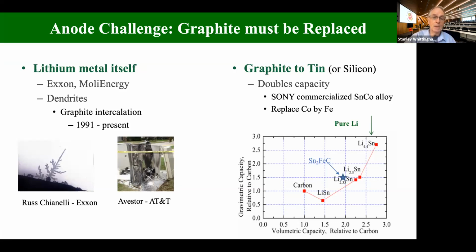They made the polymer too thin, so the dendrites grew right through it. And these lasted maybe a few months before they were all pulled off the market. So an intermediate option to going to pure lithium is to go to tin or silicon. This will double the volumetric capacity.